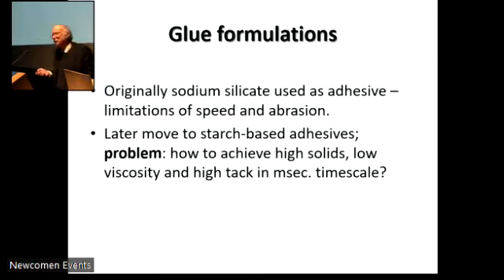How do we do this? Well, originally they used sodium silicate solution, best known as water glass, but they soon found that at any speed, the innards of the single face had got coated with something resembling granite, which meant that you could only clean the thing down with a cold chisel. So this dropped out of fashion, and instead starch-based adhesives came in. But the problem is how to achieve relatively high solids, low viscosity, and high tack in a millisecond time step.